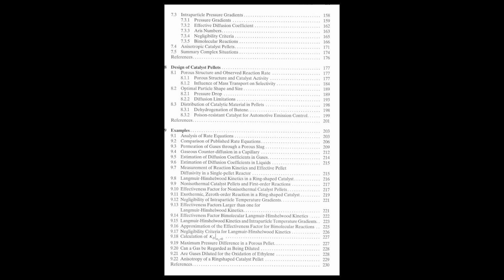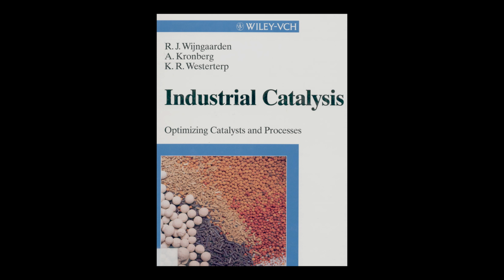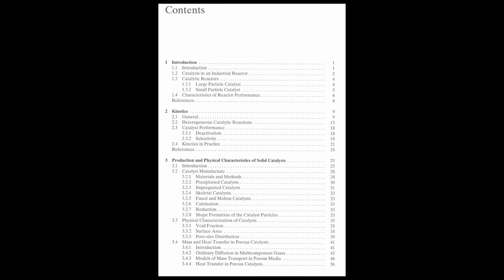further increase the local reaction rate inside the pellet, remember Arrhenius. In some cases, this can create a positive feedback loop leading to thermal instability or runaway, where the reaction rate increases uncontrollably. What happens then? It could damage the catalyst, cause unwanted side reactions, or even pose safety risks due to rapid temperature and pressure increases. The book introduces dimensionless numbers like the Prater number, which relates temperature rise to concentration drop, and the Thiele modulus, which we saw relates reaction rate to diffusion, to help characterize these temperature and concentration gradients within the catalyst.